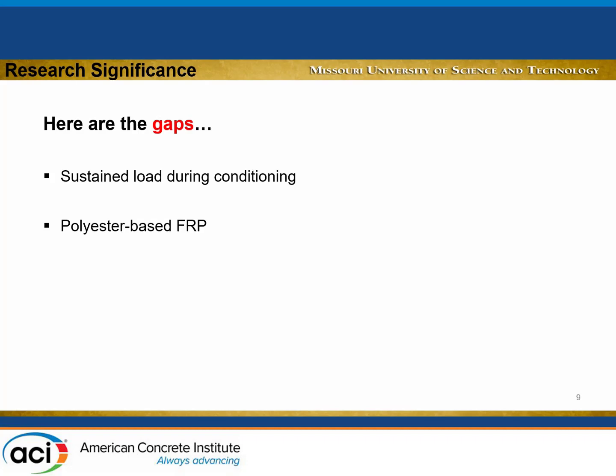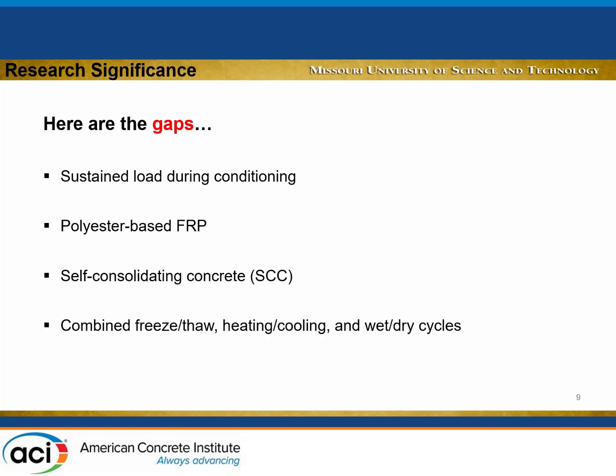So one of the things that we believe can reduce the cost is to knock down the resin. So we also try to look at polyester resin for the FRP. And then again, we use the self-consolidating concrete. What is the issue with self-consolidating concrete? You typically use higher cementitious material, and with this higher cementitious material, you have more alkalinity.